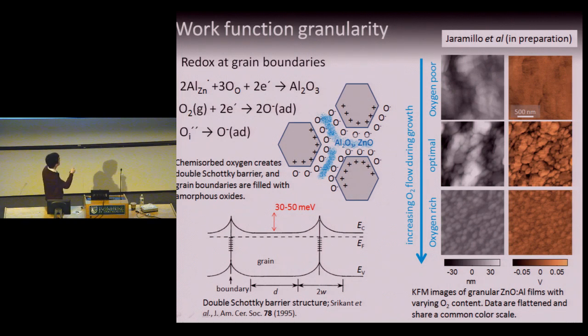Focus just on the right-hand side here. Now, these are three samples with low oxygen content, optimal, and then high oxygen content. And this color map shows you this work function measured across the film. And what we see is that actually the optimal film has a high degree of work function contrast between the grain and grain boundaries. Going further, if you remember, dark equals large work function, light equals small work function.